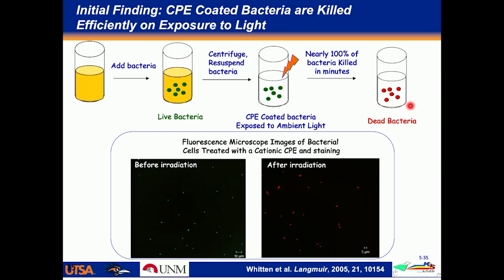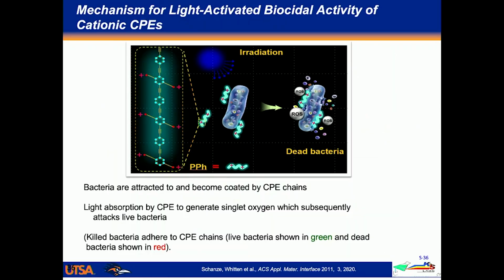The experiment I'm showing here is called a live dead assay, and a simple way to think about it is that the green bacteria in this image are alive, their membranes are intact. After exposure, the dead bacteria membranes are compromised, glow red, and that's because you add a second dye. So it's a way of measuring the cell death that's induced by irradiation. So Dave first reported this effect back in 2005, and together he and I have been working on this area for quite some time, and I'll show you some of the different results.